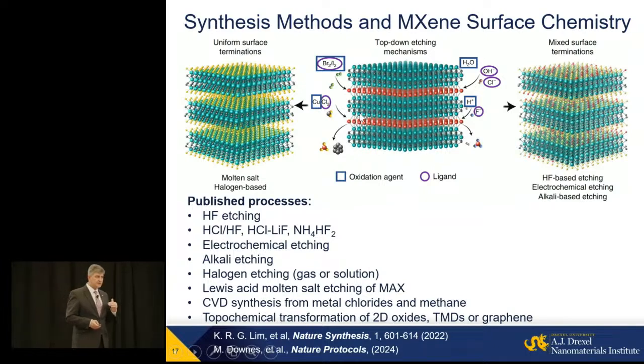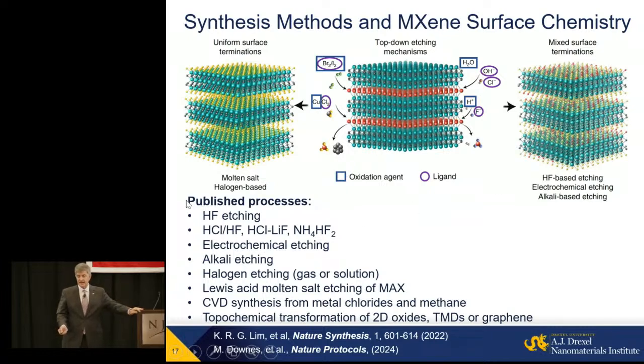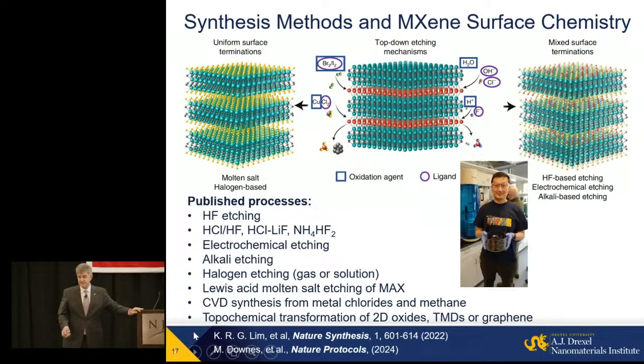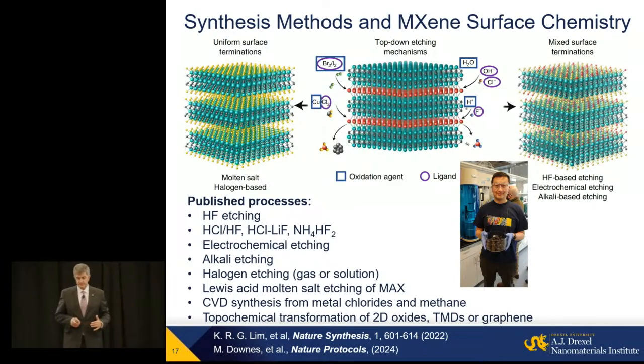And what is interesting, it appears that we can actually remove a monatomic layer of elements at the moment up to about 100 micrometer distance. Think about it: a few angstrom layer over 100 micrometers, what is the aspect ratio? Uniformly from a large volume of material, making two-dimensional material from this layered ceramic. And there are by now many synthesis methods. When we started to make them, we used hydrofluoric acid etching of titanium aluminum carbide. This is how the first MXene was made.